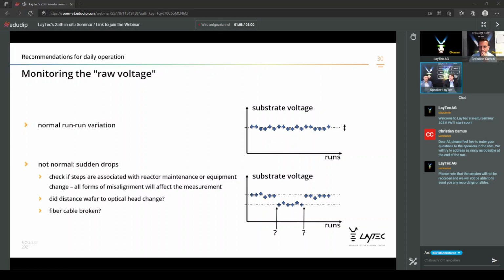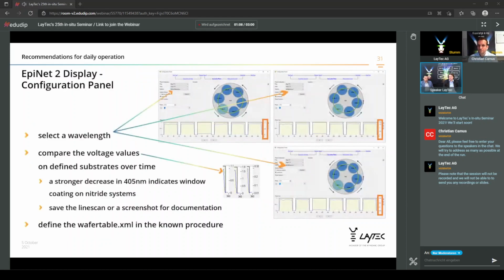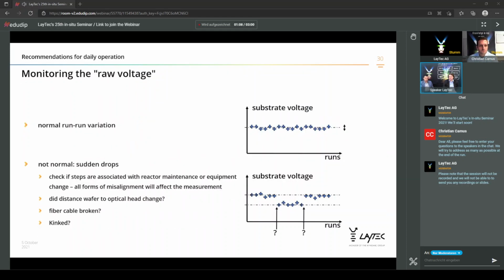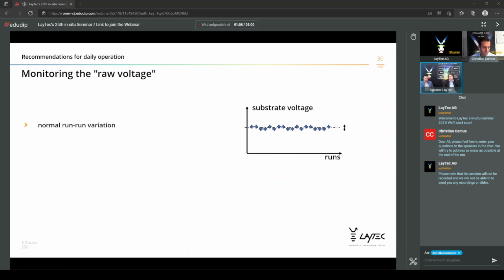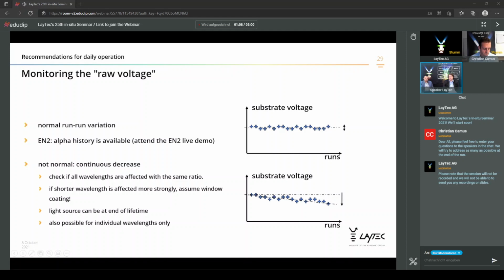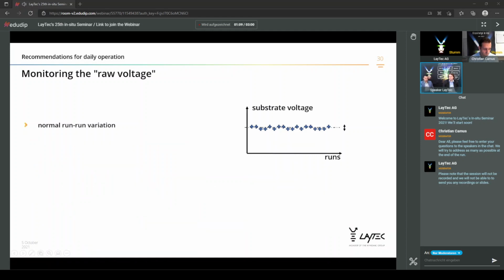So sometimes you will have one intensity, sometimes another. So you will see that kind of drops, yeah, instead of seeing a continuous decrease. Or the fibers might be kinked, or the bending radius is too small, or is changing because the fiber isn't installed properly. Well, what we recommend, if the intensity, just going back to the other slide, is decreased by 50%, you should exchange the light source.